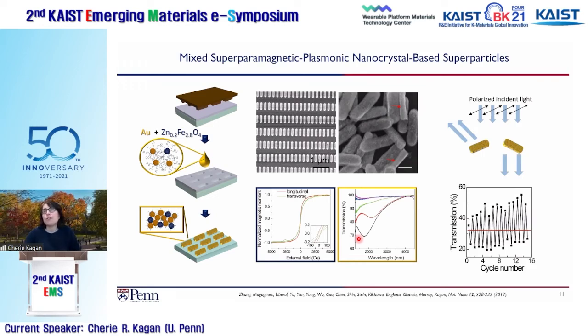I'll give you an example of what we did. We took these rods and suspended them in a solvent, and then we shone polarized light. If the light was polarized along the length of the rod at its resonance, then the light would be rejected; it wouldn't transmit through the suspension. But if we took a magnet and rotated it, the rods would change their orientation in the suspension. Now the polarized light is in an orthogonal direction relative to the rods, and the light is transmitted. So we started to think about smart windows, where you could simply use magnetic fields to control whether light passes or is transmitted through the material. That was our first foray into really mixing together different materials and their properties.